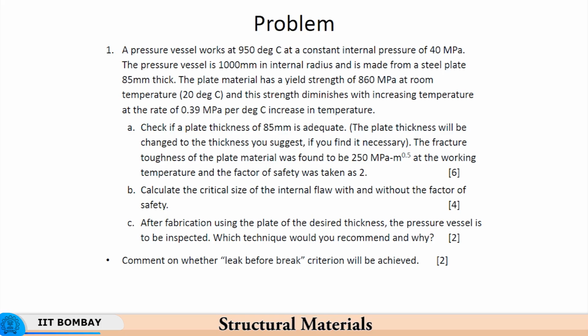So, the pressure vessel works at 950 degrees centigrade at a constant internal pressure of 40 MPa. The pressure vessel is 1000 millimeters in internal radius and is made from a steel plate which is 85 millimeters thick. The plate material has a yield strength of 860 MPa at room temperature, and this strength diminishes with increasing temperature at the rate of 0.39 MPa per degree centigrade increase in temperature. Check if the plate thickness of 85 millimeters is adequate. If you feel that plate thickness is not enough, it will have to be changed to the thickness that you suggest.